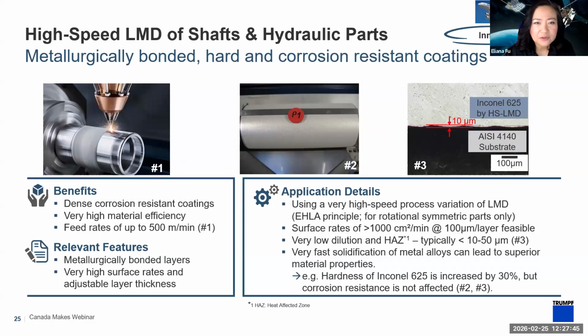So as another sort of extension of that, we have this high-speed LMD process, so laser metal deposition. And you can think of a LMD structure as a big giant weld. So we're basically applying molten material on top of itself. And in this case, this is also another learning that has come from the automotive world, where you're trying to create a dense corrosion resistant coat with very high material efficiency. So you can move pretty fast. You can deposit the layers as you require. For example, this is on a rotating spindle, and you have metallurgically bonded layers. So you have a very good final strength.